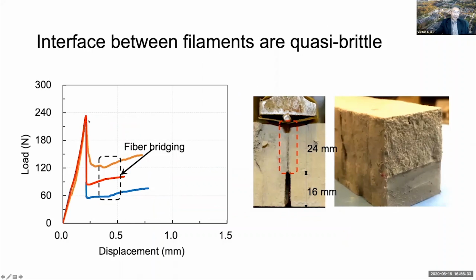Not unexpectedly, we see a brittle behavior after the peak load is reached when the crack extends along the interface. But perhaps somewhat surprising is the fact that we see in all three specimens a kick up of the load deflection curve after the initial drop, most likely a result of some amount of fibers crossing those two adjacent printed layers. This is likely a result of the interpenetration of the two layers of green ECC.